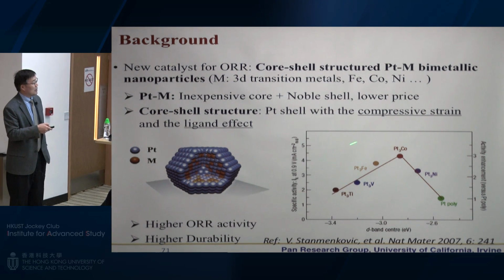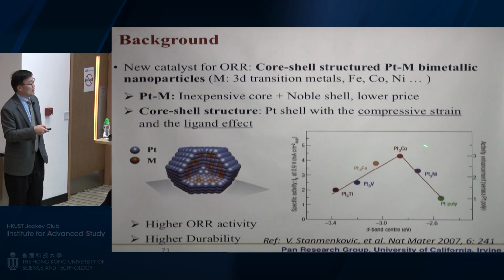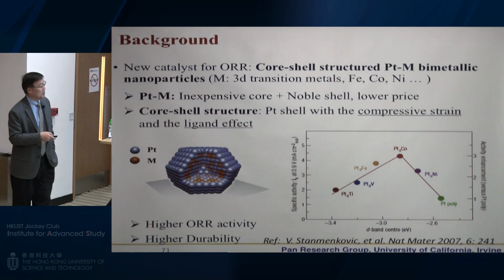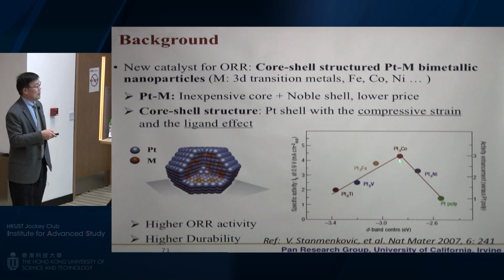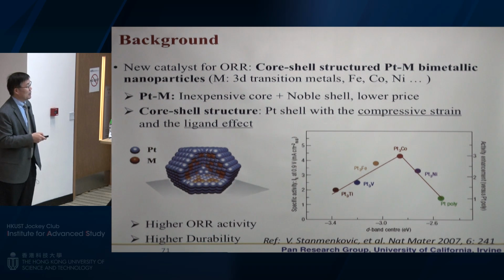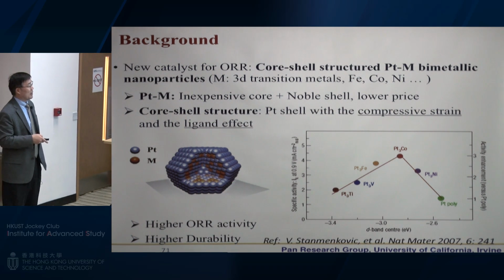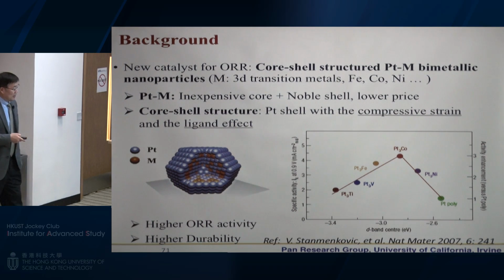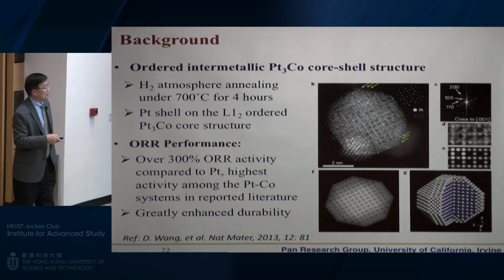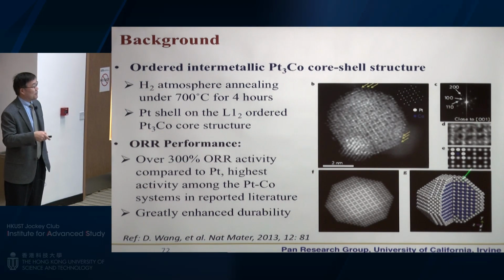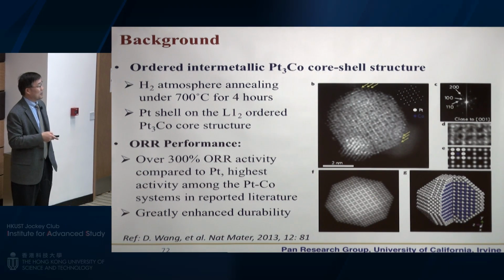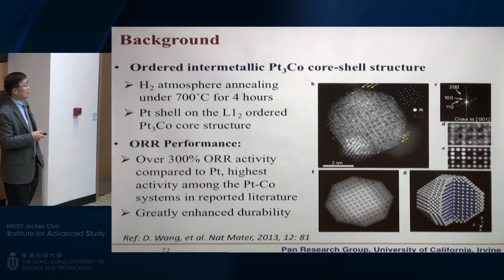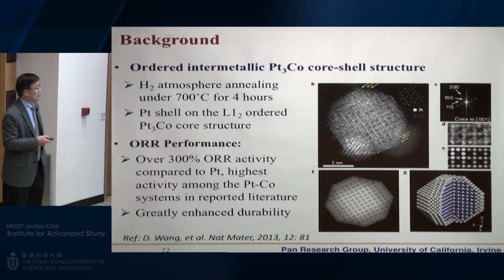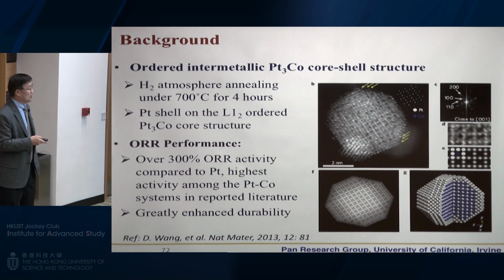And also, a recent study showed that cobalt alloy on this particle has an even higher activity. You see, with 25% of cobalt, this alloy catalyst has a much higher activity for the fuel cells. Just a few studies have been published, especially using atmosphere and seeing the structure change, order, disorder, and so on.